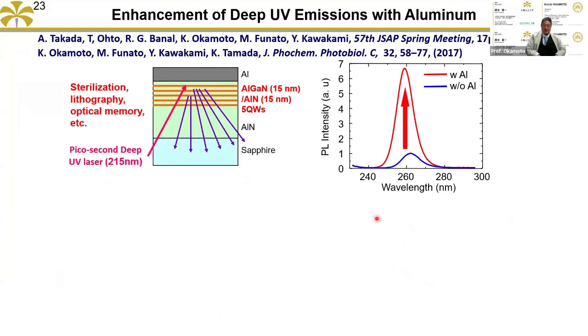Next, we want to extend to the UV light region, because UV light is very important. For example, aluminum gallium nitride quantum semiconductor structures are used for deep UV light sources, usually in the 260 nanometer region. This wavelength is very important for sterilization, lithography, optical memory, and many other things. But at the moment, there are no highly efficient deep UV LEDs. Efficiency is very low. And as I said, aluminum has a very high electron density, and the plasma oscillation is in the deep UV light region. That's why when we just put on the aluminum, we obtained 7 times enhancement at 260 nanometers.